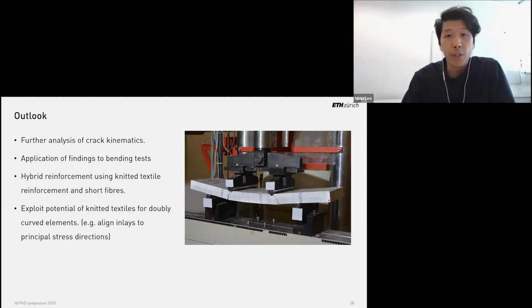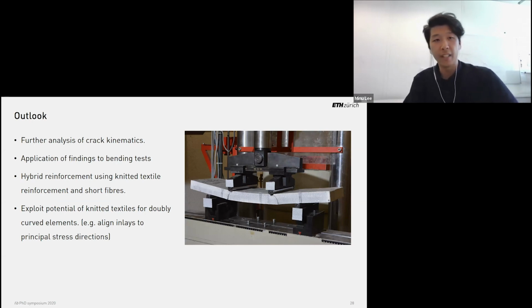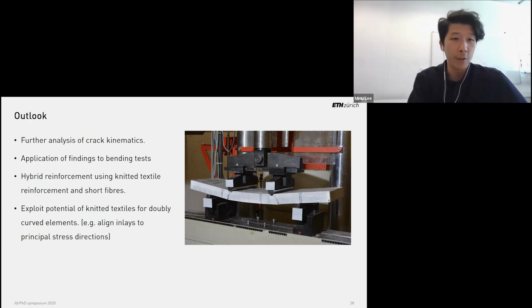And at the moment, as we said, we're looking at the further analysis of the crack kinematics. We also started to apply the findings to bending tests. We also want to have a look at hybrid reinforcement systems using knitted textiles and short fibers, for instance, to improve deformation capacity. And eventually, of course, we want to exploit the potential of knitted textile for doubly curved elements, where we, for instance, can align inlays to the direction of principal stresses.